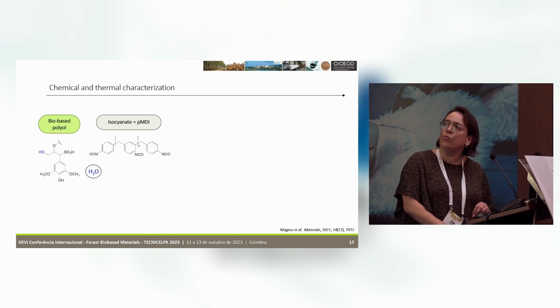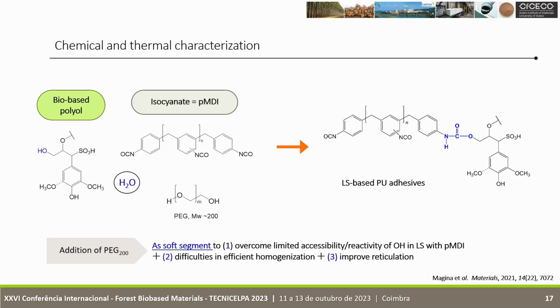So the basic formulation was mixing the lignosulfonate with the isocyanate and a bit of water, but due to difficulties in mixing all the participants of the reaction, we also studied the addition of polyethylene glycol with low molecular weight, to overcome the limited accessibility of the hydroxyl groups in lignosulfonate, but also to promote more efficient homogenization as well as to improve reticulation.